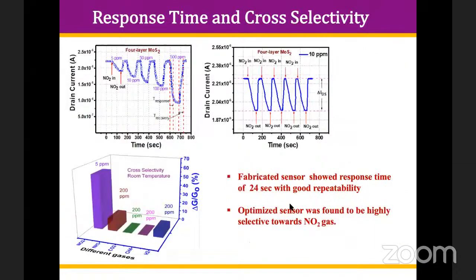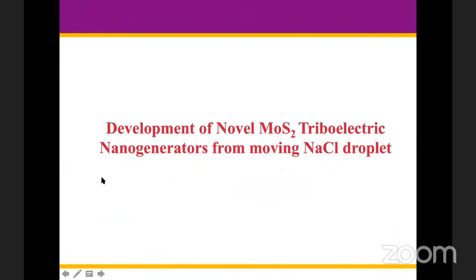I can skip this part quickly now because time is running out. So these are, you can say, the repeatability of the experiments and the selectivity, which ensures that the response is much higher for the NO2 gas as compared to ammonia, CO2, CH4, whereas we use a very high concentration of other gases, 200 ppm, and only a very small concentration of NO2, 5 ppm, which clearly shows that these sensors are highly selective to the NO2 gas, not the other ones.